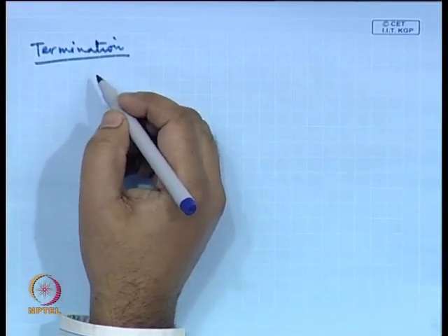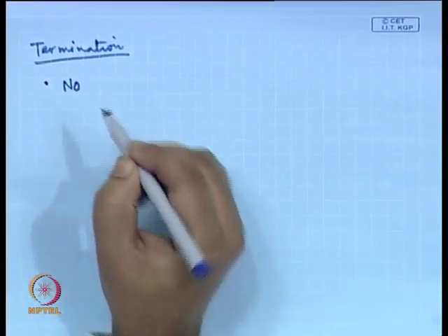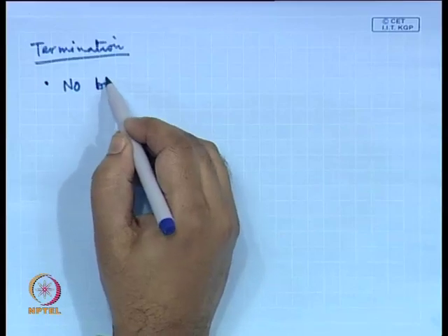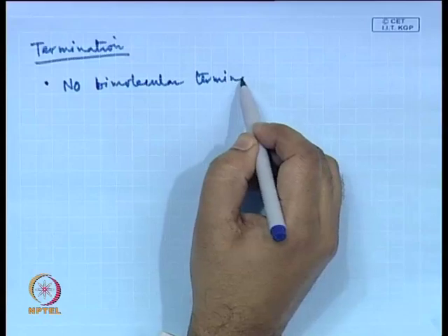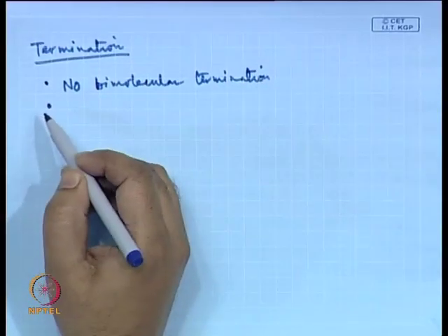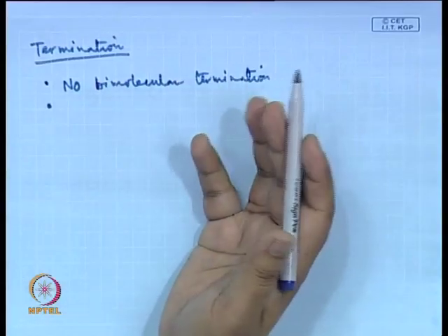for anionic polymerization. If you recollect from our discussion, in anionic polymerization you have no bimolecular termination, and in fact, in the absence of any side reaction, if you have taken care of the reaction conditions in such a way that no impurity is present and you have taken care of all the other purity aspects, then most of this anionic polymerization actually propagates without termination.